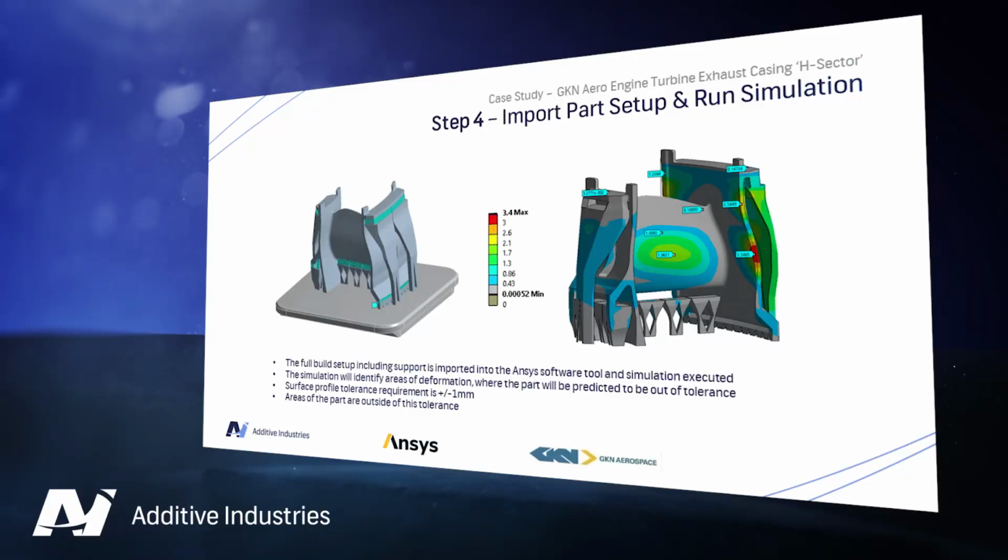Now, based on the supports and the orientation that was selected in step number 2 and number 3, an initial part was printed. So the initial part didn't have any kind of input from the simulation tools, but the idea was to be able to compare the simulation results with the scan geometry of this first try. So in this part, there were not really clear cracks or failure of the support structure, but there was some evidence of large deformation, a kind of buckling, and also a shift line at the top of the casing.